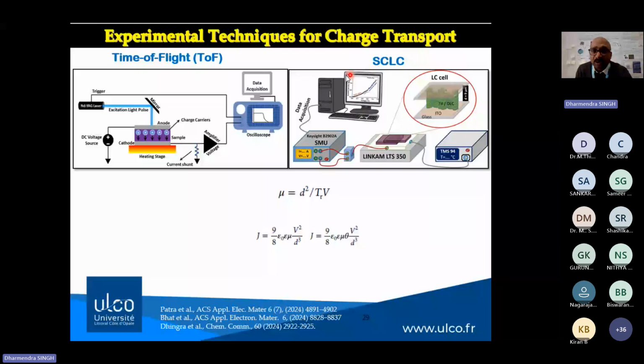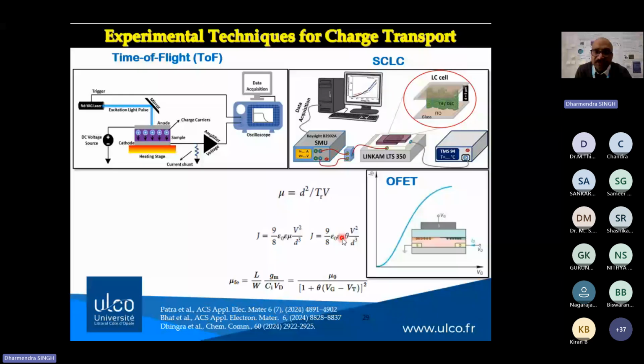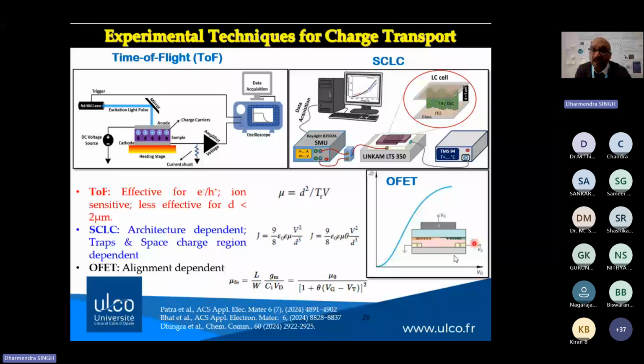So the current voltage characteristic will have two parts, one ohmic region and one non-ohmic region. In the ohmic region, the current is directly proportional to the voltage, and in the non-ohmic region, the current will be proportional to V squared. Following the Mott-Gurney equation, you can estimate the charge carrier mobility. The third method to measure the charge carrier mobility is OFET. You have to fabricate organic field effect transistor devices in order to estimate the charge carrier mobility.